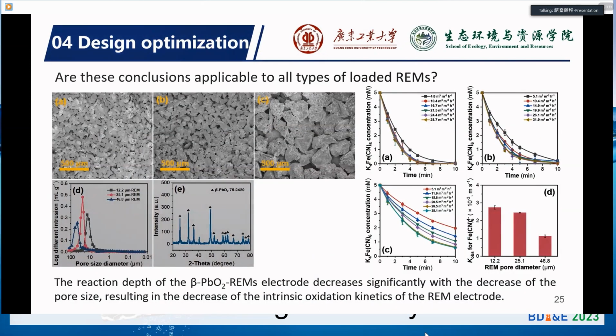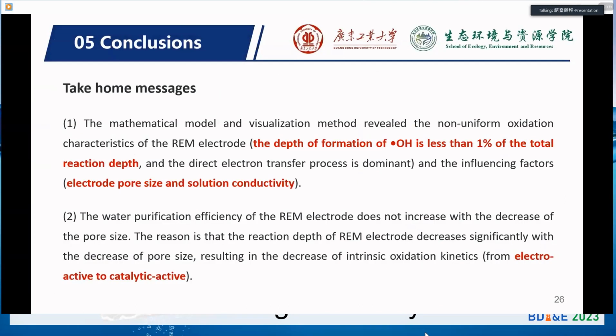Also, our findings are not only limited to the tin oxide we investigated, we also evaluated the performance of other metal oxide electrodes, such as lead oxide and also Ti4O7, and we find that the reaction depths decrease significantly with the decrease of the pore size below the critical value, resulting in the decrease of the intrinsic oxidation kinetics of the REM electrode. So these are the take-home messages of this presentation.